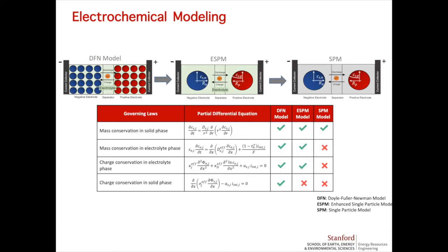And the electrolyte has its own dynamics. So we model the charge conservation in the electrolyte phase. Down to the spectrum here, the single particle model makes the assumption that the electrolyte dynamics do not change, and so all we care about here is the mass conservation in the solid phase. This is a good approximation if your system is operating at a low C rate. And so SPM and ESPM perform very similarly when the C rate is below, for example, 3C or so.